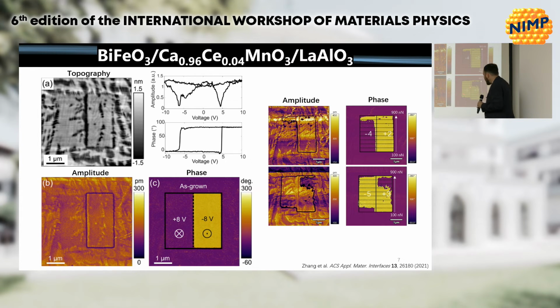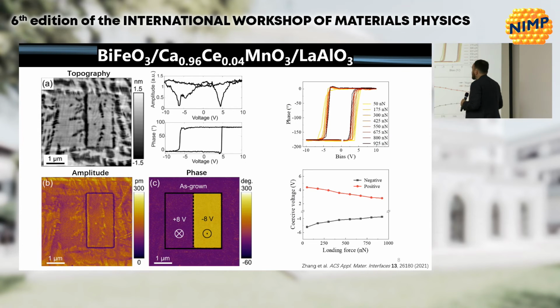Now, just increasing by 1 in both directions. So again, plus 8 switching, applying minus 5 along with a force, so minus 5 at 200 nanonewtons, it starts to switch. And for plus 3 volts, it starts to switch when we get up around 700 nanonewtons. So the influence of the force on shifting the coercive bias, I think, is clear here.